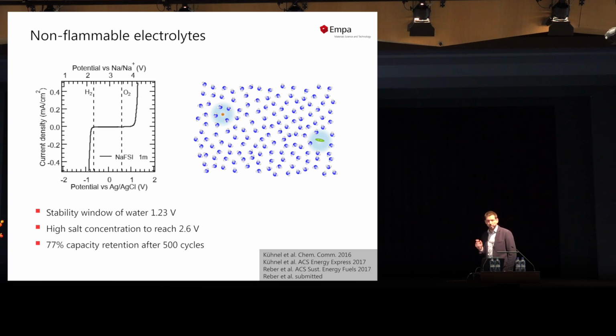Of course, water has a problem. Water has an electrochemical stability window which is limited thermodynamically to 1.23 volts. If you go to lower potentials, you evolve hydrogen. At higher potentials, you evolve oxygen. You want this in an electrolyzer, but definitely not in a battery. So the trick that Darwin and Ruben are using, they are going to very high salt concentrations.